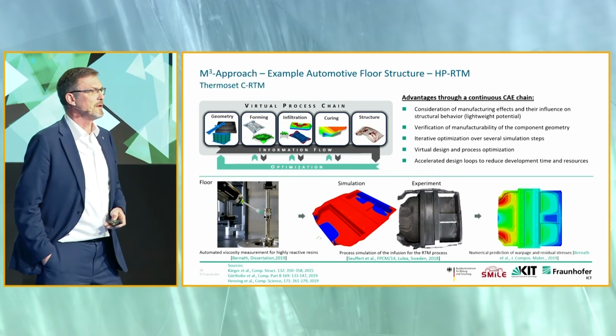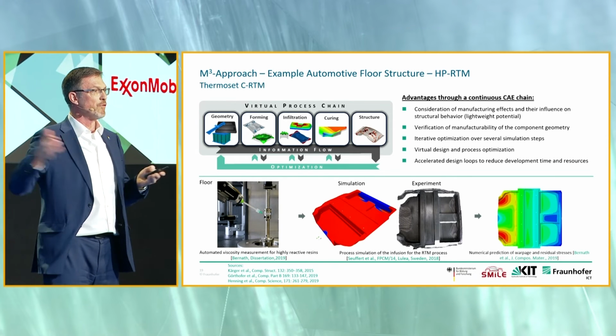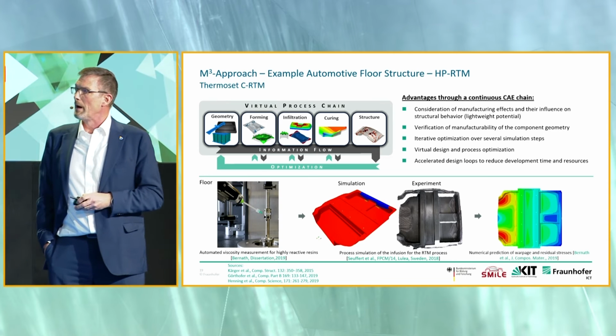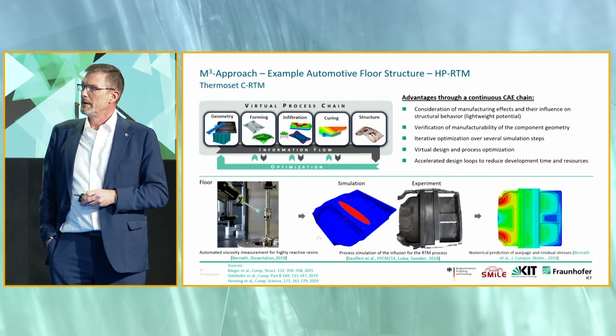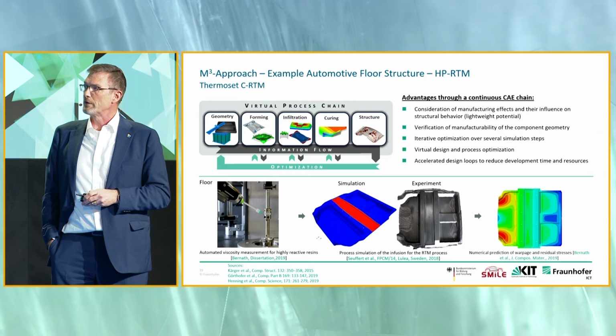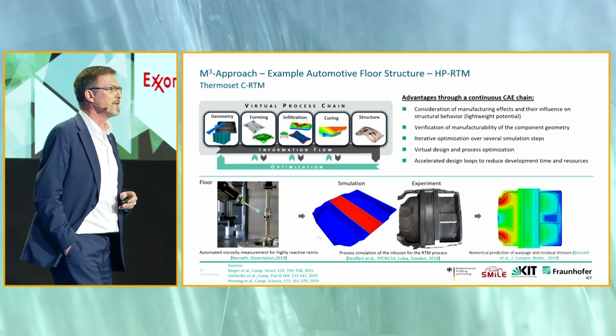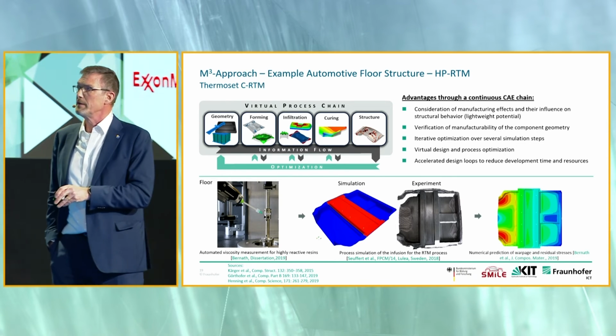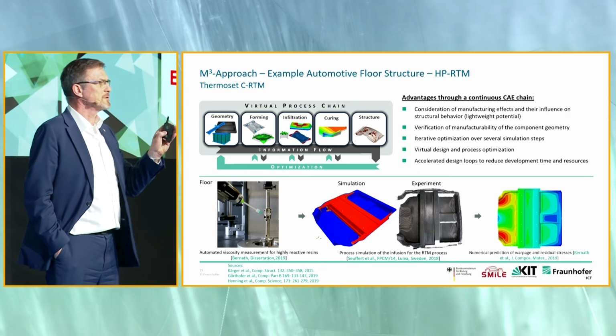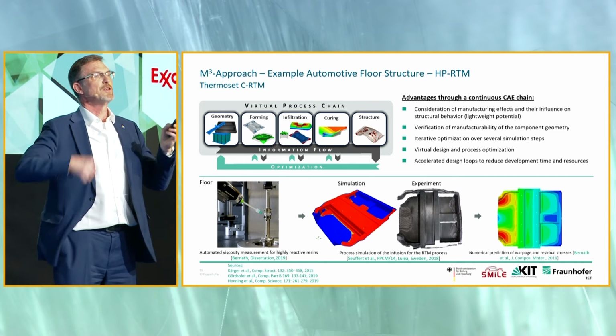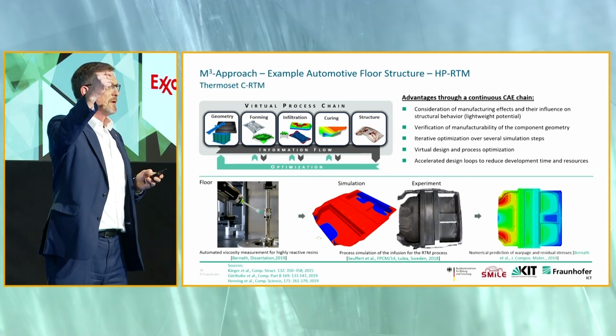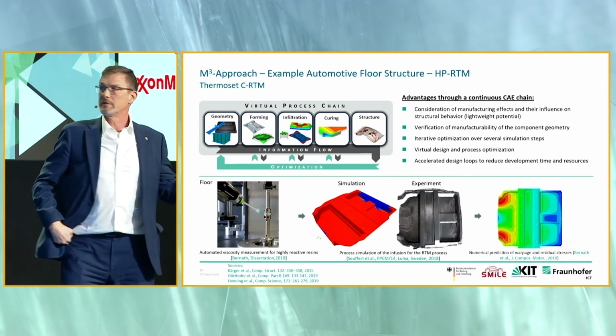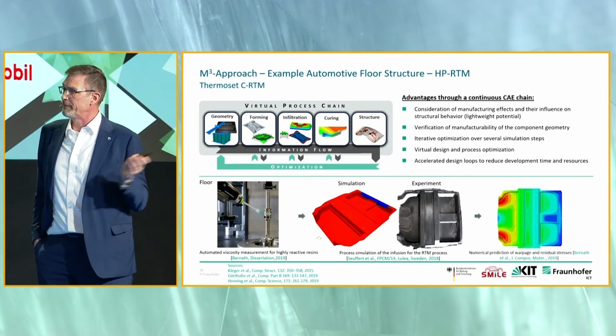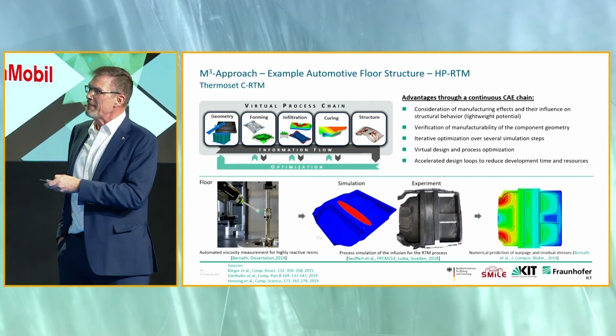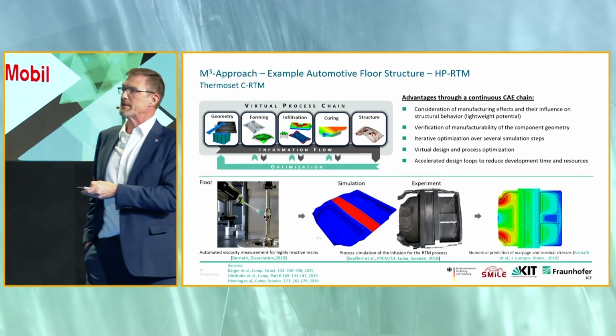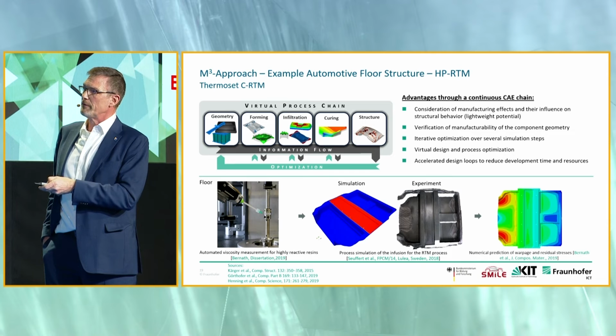So it's a pretty complicated part when it comes to different wall thicknesses and flow distances, and we apply our software or our algorithms to understand where to inject and what speed to inject in order not to move the fibers, depending on the viscosity of the resin, to get basically the fastest possible infusion without any dry spots, and then to be close to the gel point and snap cure with the chemistry that you've seen in the presentation before. And then basically after we have the manufacturing secured, that's just an experiment to verify our codes.